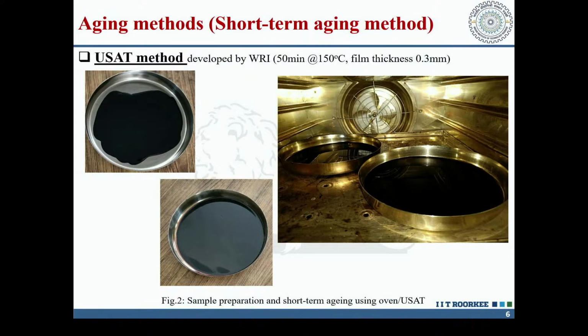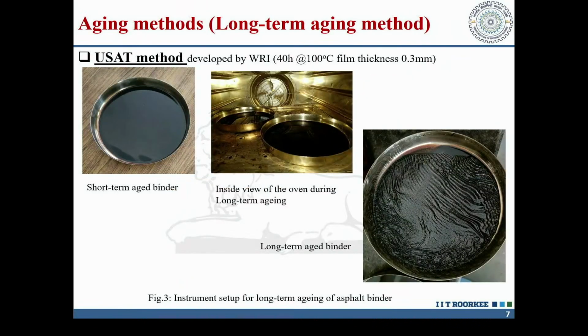We are using the USAT method for 50 minutes. We are putting it at 150 degrees centigrade with the film thickness of 0.3 mm. So you can see the photographs. It is being done like that. Then it is showing you the short-term aging binder in the first photograph. In the second, it is the inside view of the oven during long-term aging.